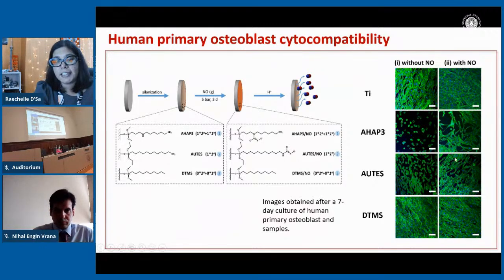Whereas on the AUTES surface, as we had previously seen, the cells do like these surfaces and they are displaying a bit of a positive response to the surface, and they have the cobblestone morphology that is indicative of osteoblast function. So we are getting a positive cell response on this type of surface, which has a bactericidal capability, not as much as this type of surface, but the results are promising.